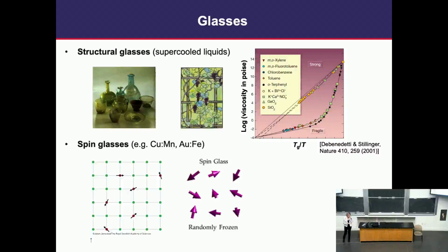Okay, so in addition to structural glasses, there are also spin glasses, where people put magnetic impurities, magnetic ions like manganese or iron, into good metals like copper and gold. And at low enough temperatures, because they are randomly placed in a material, these spins get frozen. They cannot really move because each spin interacts with all the other spins, and they don't know which way to point. Maybe one pair prefers them to point this way, another the other way. So in other words, there is a frustration in the system, and people usually illustrate frustration by showing the example of 3 spins on a triangular lattice. If they interact with the antiferromagnetic interaction, in other words, spins prefer to point in the opposite direction, you can place 2 spins, but what is the third one going to do? So the system is frustrated.